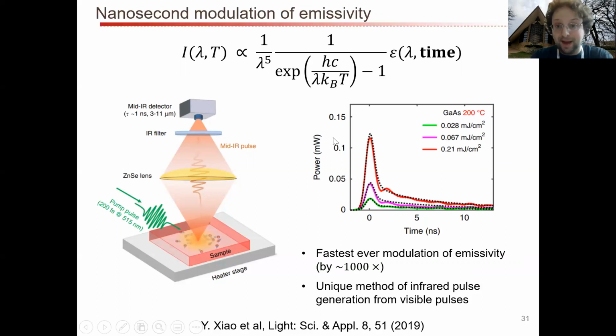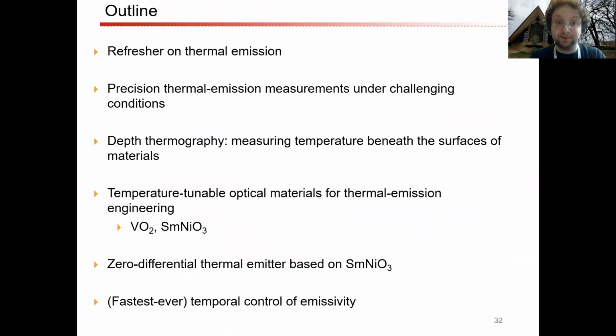And so this is the result. You can see the power versus time, this is experimental for different fluences of the pump laser, and for the gallium arsenide at 200 degrees Celsius, you can see that there's this first pulse, and then there's this long decay, and this pulse is on the order of a nanosecond. This decay is on the order of a few nanoseconds. So this is, as far as we understand, the fastest ever modulation of emissivity by something like a factor of 1,000. So we're quite excited about this result. It's also a rather unique method of infrared pulse generation from visible pulses.